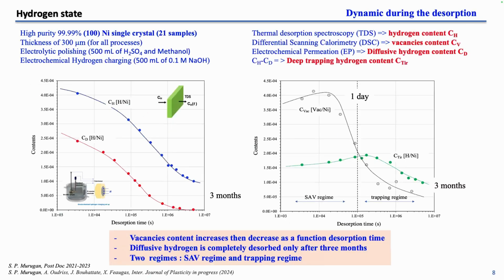We also follow the evolution of the concentration of hydrogen of different types, and the concentration of vacancies using different techniques, summarized like that. Here we show, during the desorption for the (100) orientation, the total concentration of hydrogen. It's diffusible hydrogen, and we need 3 months to have a complete desorption of hydrogen after precharging of 7 weight ppm in this material.